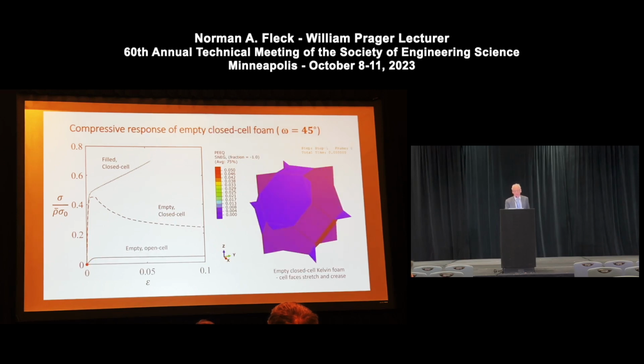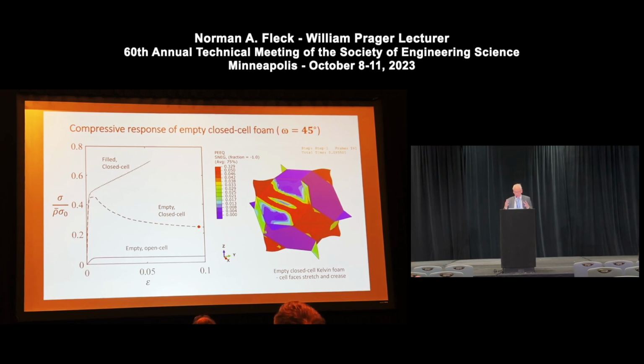Okay. Now I take the case of an empty closed cell foam. So it's the same lattice, but now we've put some cell wall material into the faces, and here's the response. So again, it's a softening response. It's more evident that the stress strain curve is dropping. So one would expect macroscopic instabilities to occur, crush bands, and so on. The cell faces may stretch in some directions in tension, and in compression, because the cell faces are thin, wrinkling and creasing takes place. But overall, there's a geometric softening.